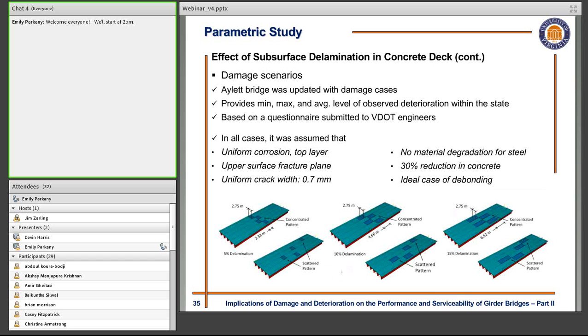So in order to understand the behavior of the system under the effect of delamination and corrosion of the rebars, we updated one of the bridge models that we had, the Aylett bridge, with 6 representative cases that, again, we selected based on the responses we got back from the VDOT engineers. And as you can see in these figures, we selected 3 levels of propagation from 5% to 10% to 15%.